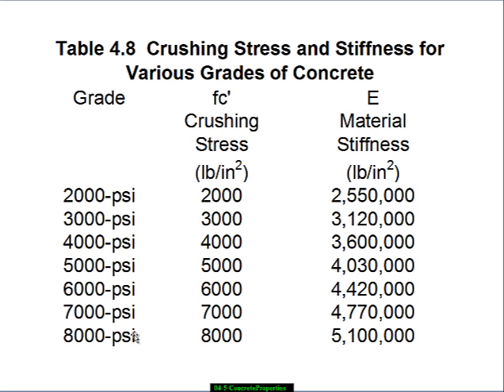The table went up to 8,000 PSI. The Burj Dubai is slightly over 8,000 PSI, and it's a three-component mix: water, Portland cement, and fly ash. They managed to pump that in a single stage essentially to the top of the world's tallest building, if you ignore the 50-story steel tube at the top. It's possible to get really exceptional grades, particularly if you work in a part of the world where you have excellent aggregates, a really excellent infrastructure, and use all the modern materials like super plasticizers available today.